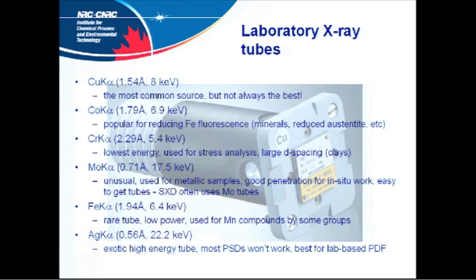Moly used to be very common in very old, even older than me, days. Moly powder instruments used to be relatively common. They died out to some extent, but now they're coming back. You'll often find these tubes lying around because single crystal work tends to use them all the time, so they're quite easy to get hold of. Iron is a pretty rare one. I only know one group that uses that. It tends to be quite low power, but it's been used for some capillary work with manganese compounds. It doesn't fluoresce and doesn't scrunch up the pattern the same as the molybdenum does.